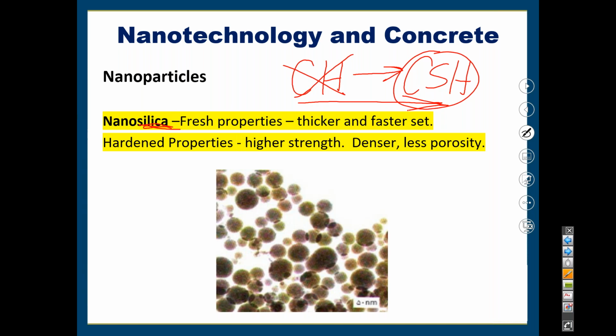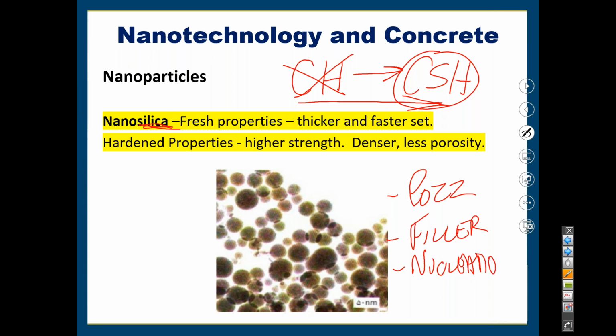and it ends up increasing that packing density. Okay, so once again, to clarify, it acts like a pozzolan. Two, it has a filler effect where it just naturally fills the areas between the CSH gel, and then has the nucleation effect as well that helps foster further hydration. So just those three things make it an excellent product in terms of it creates a concrete that is denser, has less pores, therefore has higher strength and is more durable.